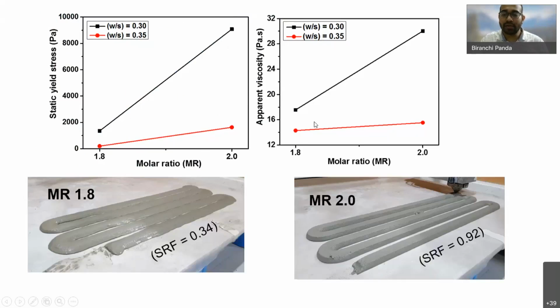So if you want to try different mix designs and investigate, of course, it is very true that when you have a concentration of 2.0, which creates higher viscosity, you will expect a material which has more shape retention compared to the material with 1.8 activator concentration. So if you're trying to develop a new mix design, it is very important to know what the critical components are that affect your viscosity. And if you know the viscosity that is needed for your application, definitely you can control the mix design to have a controlled filament as shown in this picture.